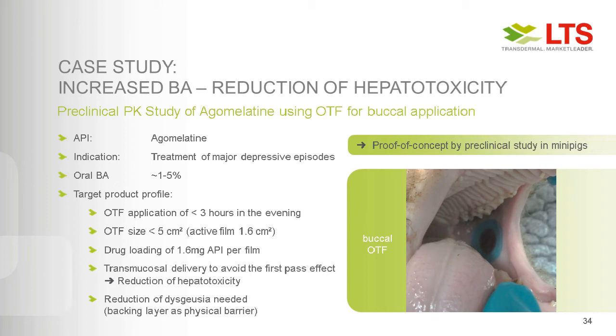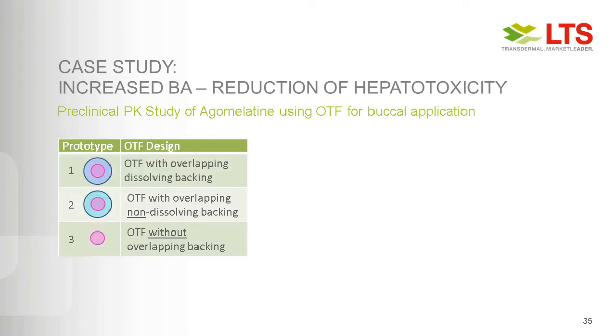And when you look here at the picture on the right, this is actually looking into the mouth of a mini pig, a Göttingen mini pig, which was used for this study. There's a limited area available for applying an OTF. Compared to the beagle dogs, this is a bit smaller, so we would not be able to apply OTFs which were much larger than that. In this case, the beagle dog was not the preferred choice for this preclinical study. We moved to the mini pigs. And you can see here the bluish OTFs with a red inner part. How it's designed, I'll show in the next slide.